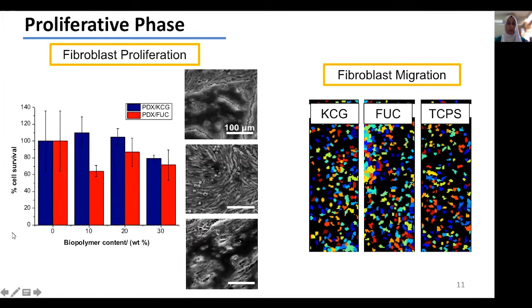We also tried to look at the behavior of the scaffold in the proliferative phase by seeding fibroblast cells on the scaffold. We tried to quantify the number of cells that were growing on the scaffolds after 7 days using MTT assay. And the graph, which is shown on the left-hand side, gives a summary of the results that were obtained. So overall, we could conclude that the cells proliferated very well on all the scaffolds, and they maintained good viability. And this was in line with scanning electron microscope images, where we could see that the cells completely covered the surface of the scaffold after 7 days.